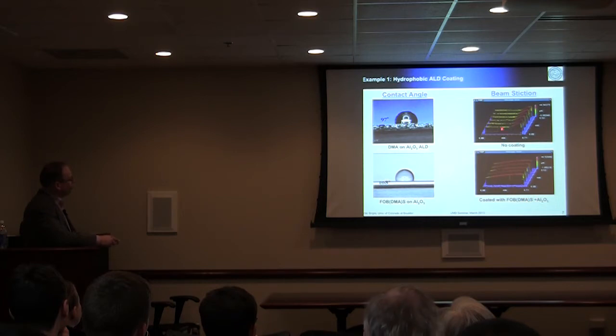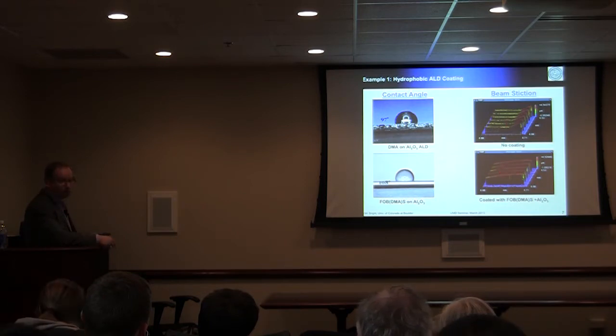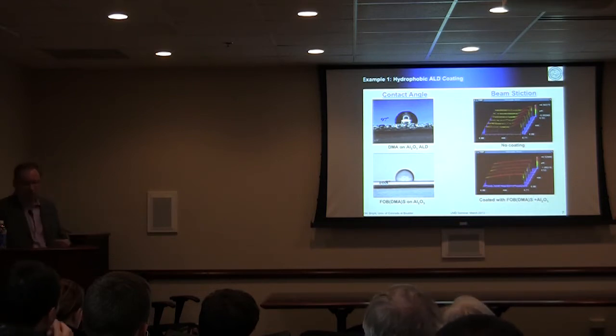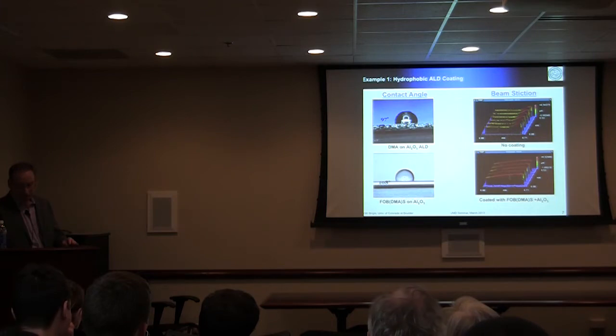But here's an example of interferometric measurement of an array of polysilicon beams coated with this hydrophobic coating. So here's an array of beams. Same beams here as shown right here. You can see these beams here all adhere to the substrate due to stiction. All of these beams are freestanding. Okay, so you can work in that direction of hydrophobic coatings.